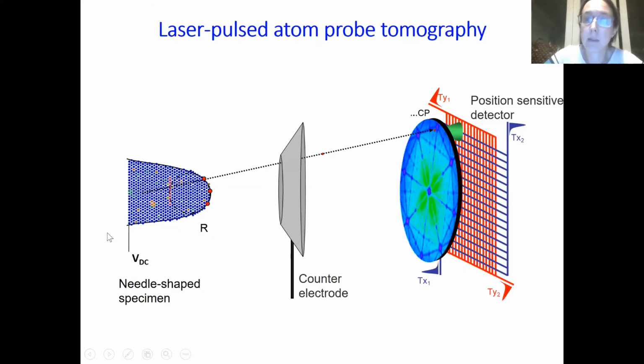We needed a new method to look at these materials. Now, there are obviously lots of different options for how you study materials, but the technique we came up with was something rather interesting. It's called atom probe tomography. In fact, we're using something called laser pulsed atom probe tomography. What we have here is a needle-shaped specimen, a tiny thin specimen, where we have made a needle which has an end radius of only about 100 nanometers. Okay? And we're going to hold that needle at quite a high voltage. Now, because it's a very sharp point, if it's at a high voltage, there's a very high electric field around this point.